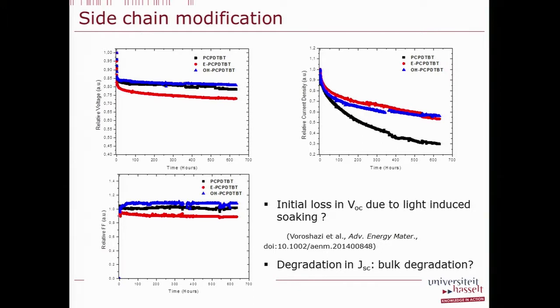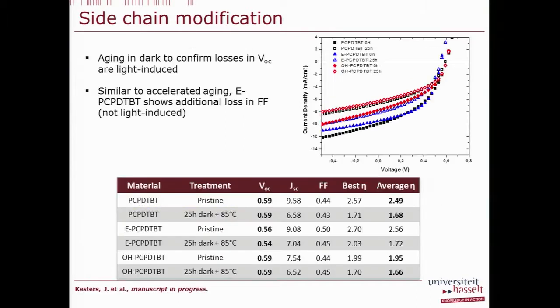So this has been done in dark, I told you, but to get these curves, of course, we had to put light on at regular intervals. So although the intention was to measure in dark, these materials received a lot of light. So what we've done is we put these devices really in the dark for 25 hours, and we looked at the IV characteristics before the aging and after the aging.